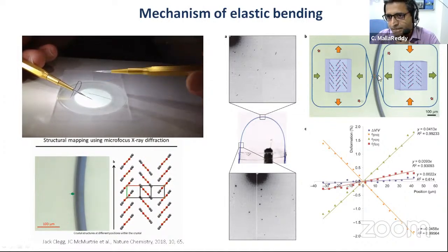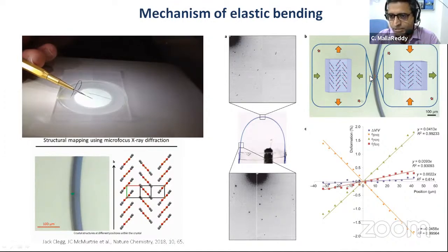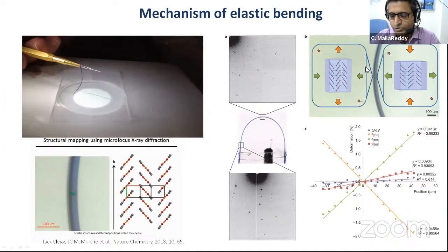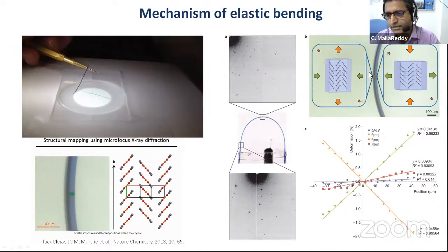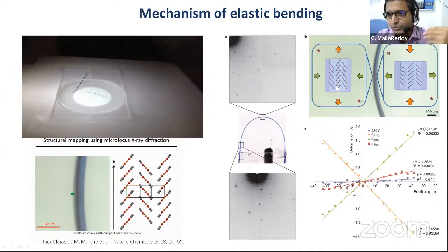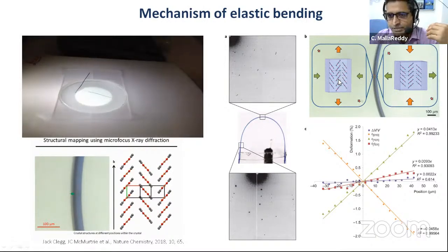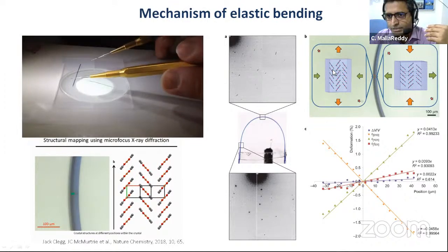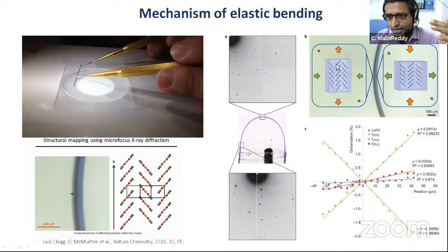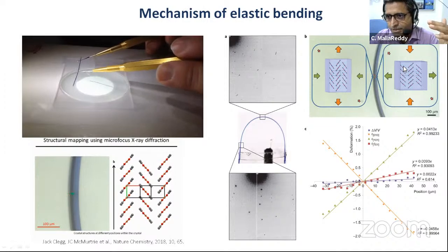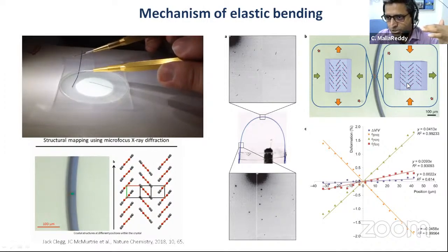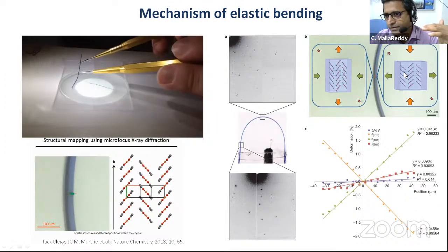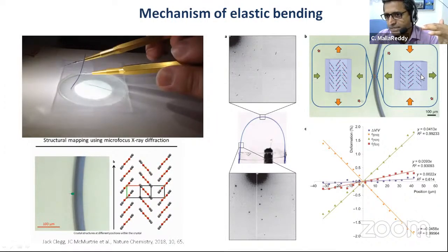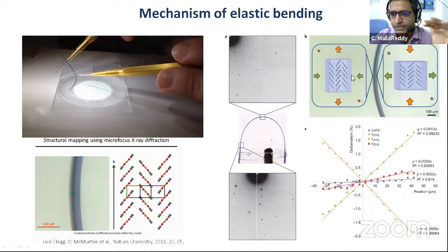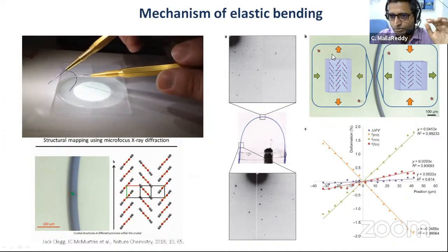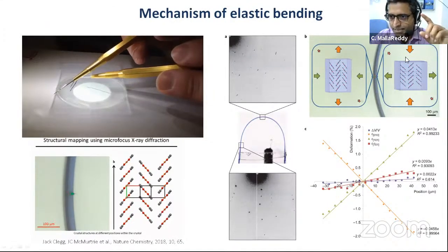So here you are compressing the layers, and that is what we said. This is a very well-known elasticity theory, right? So on the outer side you always elongate, and then on the inner side you have a compressive stress. So what is important here is the mechanism. These molecules, which are kind of corrugated, the angle between them decreases here, but here the angle increases. So when you push them, they become more or less flat across compared to this axis, and here they are turning away from this axis. So this allows you to increase the length in this direction and decrease the length in this direction.